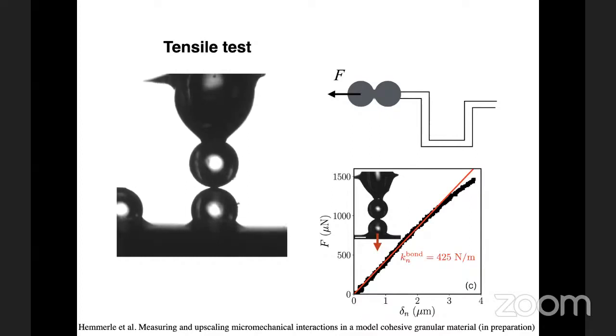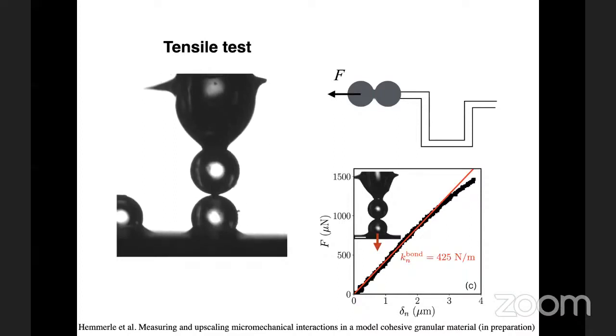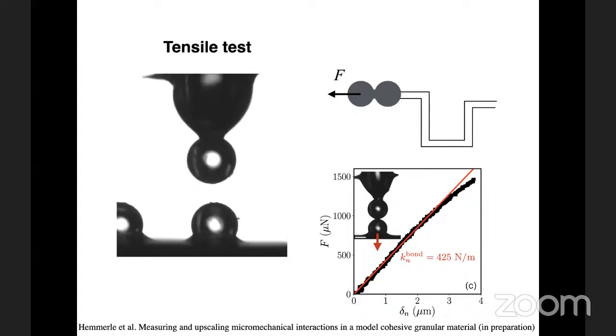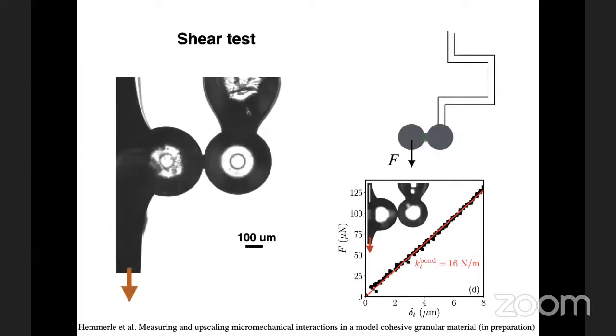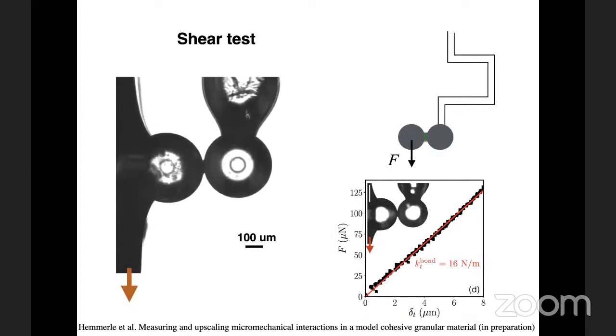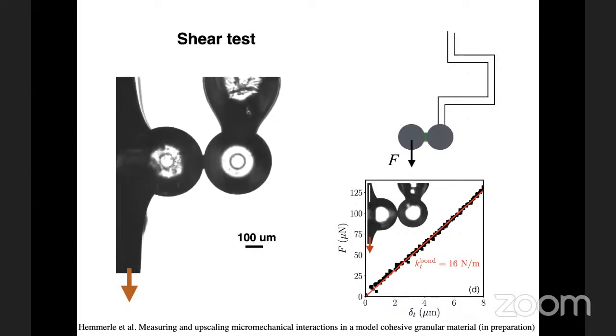So just to play again, we have experiments where we take a single bond between the particles, we stretch it, we can measure its stiffness, we can measure when it breaks as well. So we can measure a spring constant for those bonds. We can do the same thing in shear. This movie is a lot more boring because we don't stretch it until failure, but you should be able to see the particles moving against each other before and after.